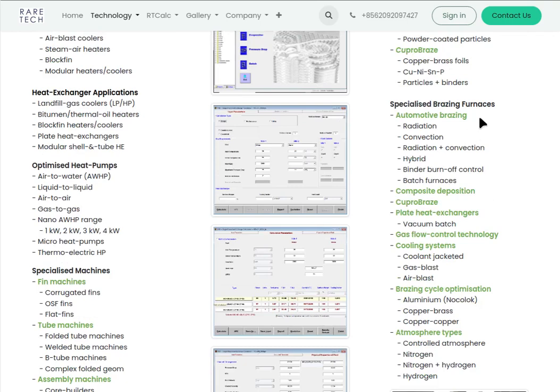And then specialized brazing furnaces, so automotive brazing, for instance radiation, which was the classic radiation from the side or the tops. How do we do that? Convection, then you've got combined or hybrids, radiation convection. Binder burn-off control is exceptionally important. If you've got binders in there, you don't want to carry them into the braze zone, because if you carry them into the braze zone, it gives you de-wetting, as I said, and off-color product. So you have to be able to manage that carefully, and I've got a few tricks that I've integrated with furnaces over the years, and it works. And then batch furnaces, how to get them to do what they're supposed to do. It's not always so easy. Again, composite deposition, CuproBraze, plate heat exchangers have been involved there also with these vacuum batch furnaces.